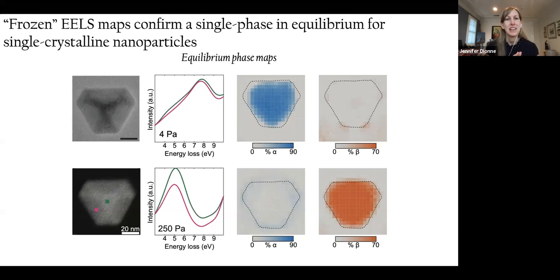And if you look at the spectra, for example, when the electron probe is focused at this green point in the center of the nanoparticle versus at the pink point, you'll notice at low hydrogen pressures, we always have a peak right around 8 electron volts, whereas at higher hydrogen pressures, we always have a peak just below 6 electron volts. And when you map that over the entire nanoparticle, we find that for single crystalline particles, we're always in a single phase regardless of the hydrogen pressure we're at.